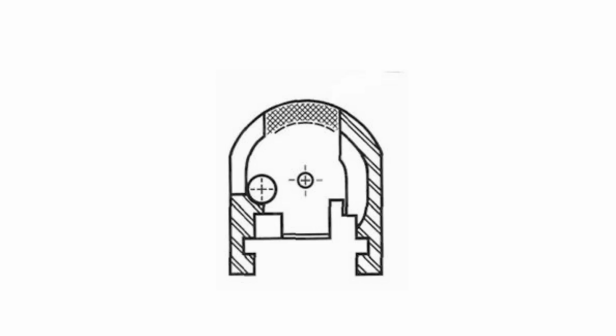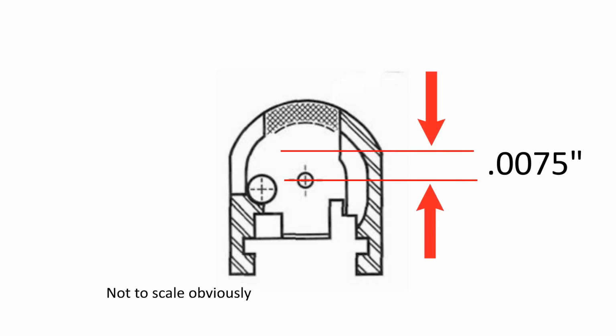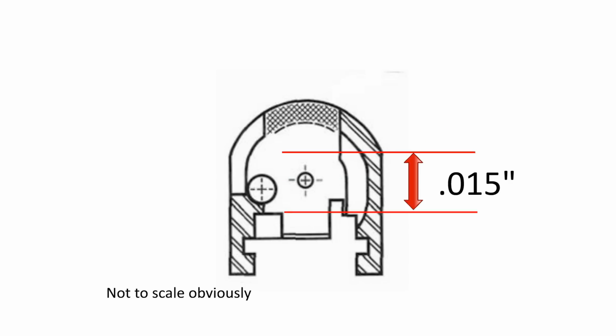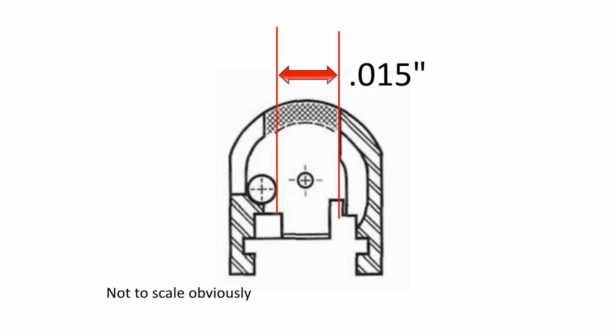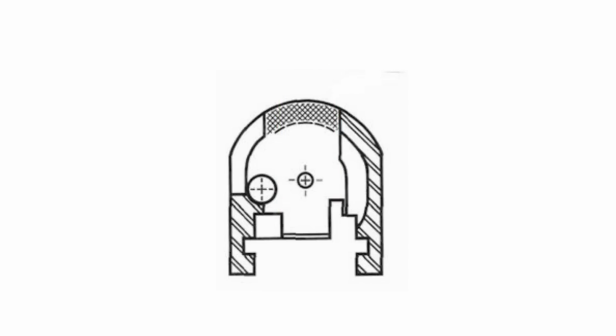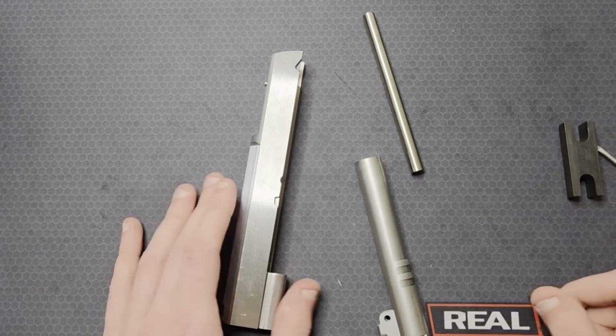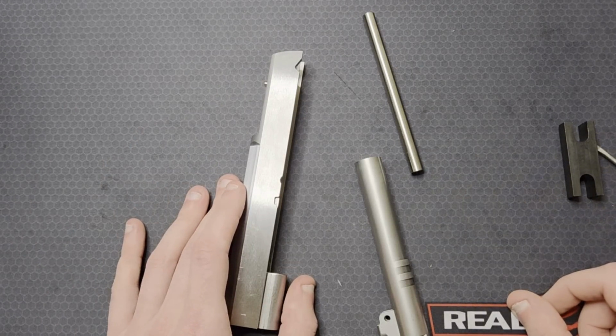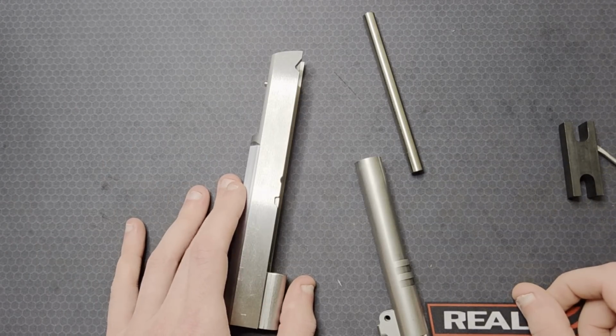I calculated that there is an allowance for the firing pin port to be displaced from the chamber center by about 7.5 thou. So a 15 thou range in the vertical and horizontal direction based on the dimensional tolerancing of the barrel and slide mating features, clearances, and firing pin port location. This is a rough calculation. I'm guessing the acceptable operating range is a bit wider than that.